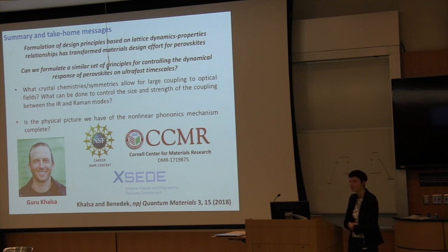Okay, you have a question, please? Gadolinium was on the left-hand side of this forbidden region. Samarium was right on the edge of the right side. Can you move down? That was our initial idea, to start with samarium. But before we got really deep into this project, we did a whole bunch of checks to make sure that within our DFT model we could get the crystal structure right, the lattice constants right, and the right magnetic ordering. With samarium, DFT was not able to predict the correct magnetic ground state. So that's why we went with gadolinium.